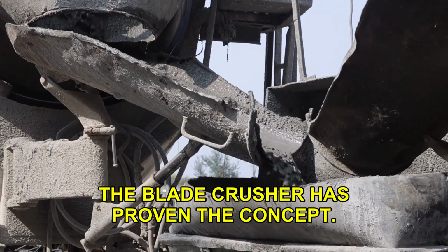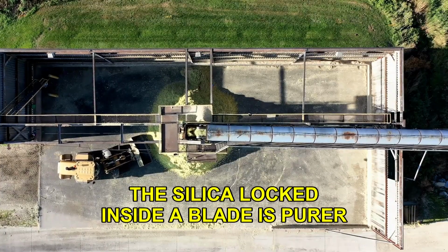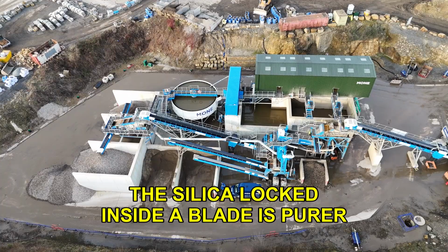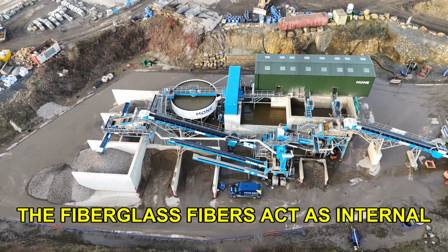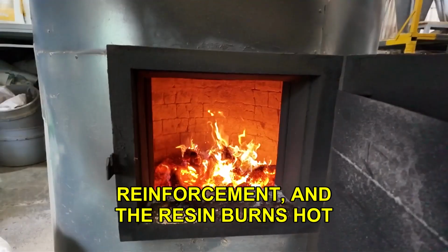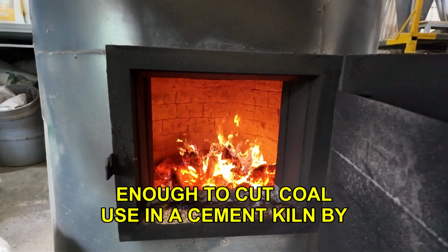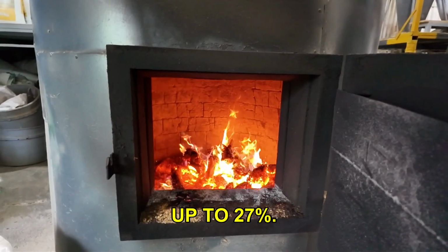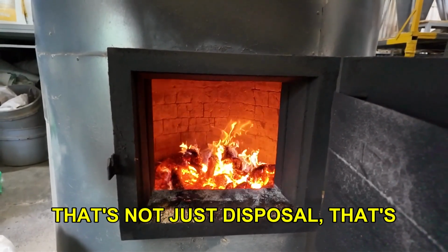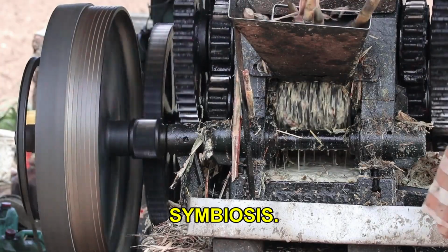The blade crusher has proven the concept. The silica locked inside a blade is purer than mined sand. The fiberglass fibers act as internal reinforcement, and the resin burns hot enough to cut coal use in a cement kiln by up to 27%. That's not just disposal, that's symbiosis.